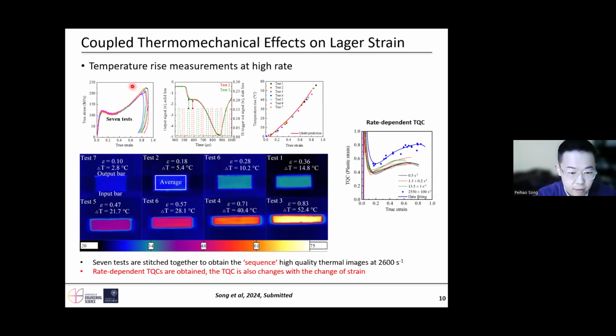So in here, I developed a new method. I controlled the triggering pressure during the Hopkinson bar test. This enables me to get a very similar stress strain curve from 7 tests. And I changed the triggering time of the IR camera to make sure I can get the IR signal of the thermal data point at different stress or strain. And I use time axis to shift them so we can get the sequence of high quality thermal images and thermal data. I calculated the Taylor-Quinney coefficient here. At the lower strain rate, I can get a continuous thermal image, and at the higher rate, I get data points. The result here is the Taylor-Quinney coefficient is also changed with the change of strain.